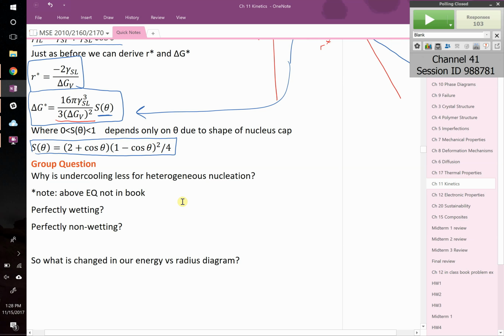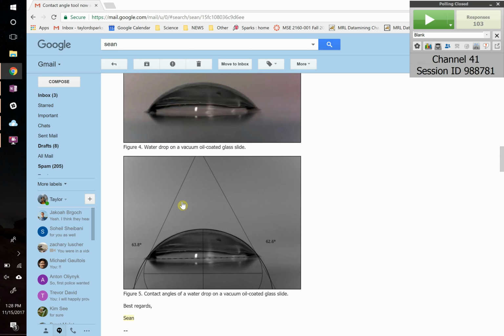Yeah. It's not tangent to the sphere? Kind of, yeah, it is. It's the tangent at the point where the droplet touches the surface. It's that angle that it immediately leaves with. So you could say it's the derivative of that tangent, I guess, as it approaches the interface. Yeah, Rob? Between heterogeneous and homogeneous, it has the same R star. They have the same critical radii size. That's really important, but they have different activation energies.